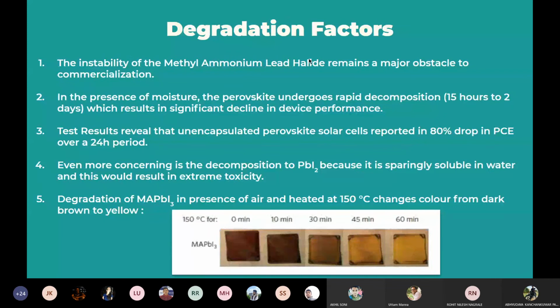Okay, so let's talk about the degradation factors. First of all, the instability of methylammonium lead halide, or in this case we are using iodide. That's the main obstacle for commercialization. Next, in the presence of moisture, it undergoes rapid decomposition, which results in a significant decline in device performance. By device performance, I mean the PCE, the power conversion efficiency of the solar cell, which is reported to drop as much as 80% over a 24-hour period due to this.